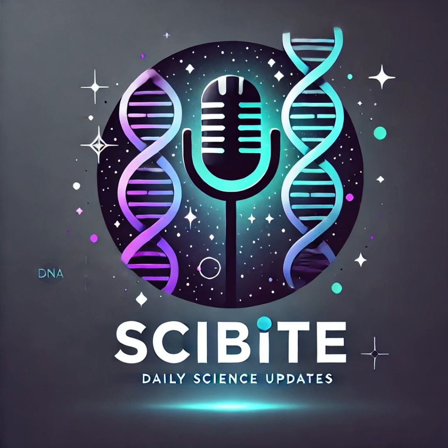And that brings us right to the core finding, the sort of aha moment in this research we're looking at. Yes, they've done it. Scientists have managed a breakthrough. Don't bury the lead. What did they achieve? They have more than doubled the power conversion efficiency of these all-organic cells. More than doubled. Seriously. So from that roughly 4% baseline we were talking about, they've now demonstrated 8.7% efficiency. 8.7. Okay, wow. That's a significant jump.